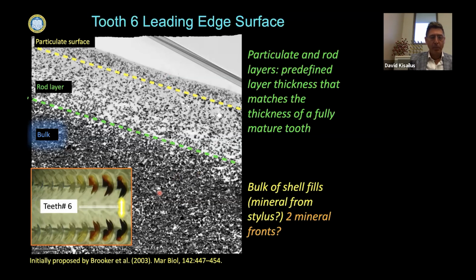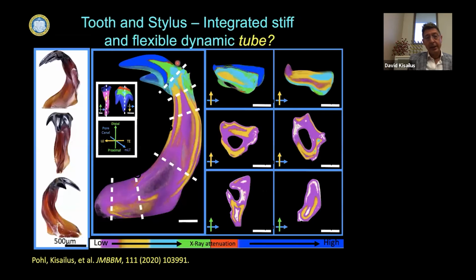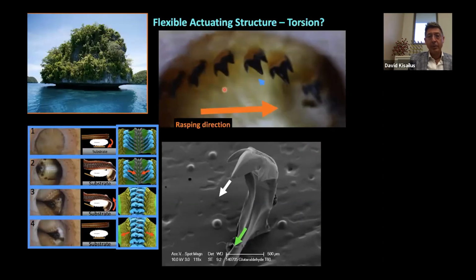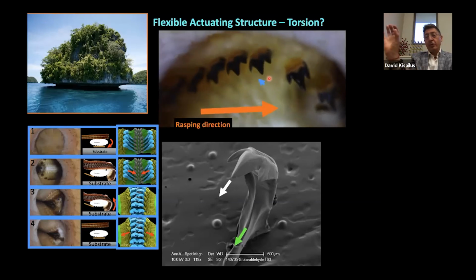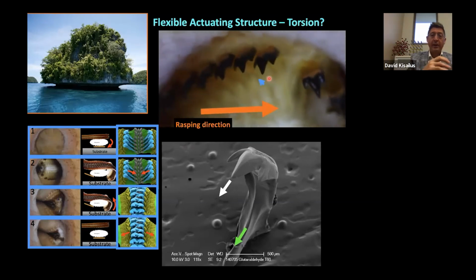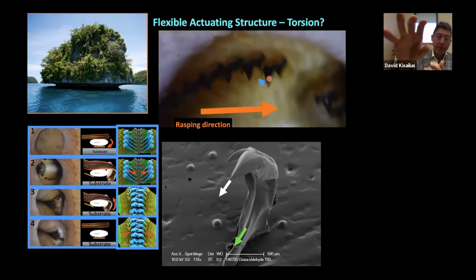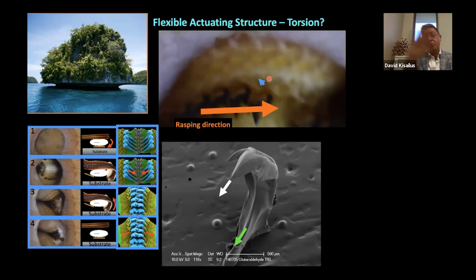So this was proposed by Leslie Brooker, that there may be actually two mineralized fronts, both from the epithelial tissue and maybe from this stylus, that structure that supports the tooth, this flexible arm. And you can actually see the stylus is actually a hollow tube. And actually, in terms of mechanics, during rasping, it actually serves to avoid any catastrophic failure. It supports the tooth, enables force transduction, but it actually has to be flexible as well so that it doesn't break. And it also has to be able to fold back up into the teeth.